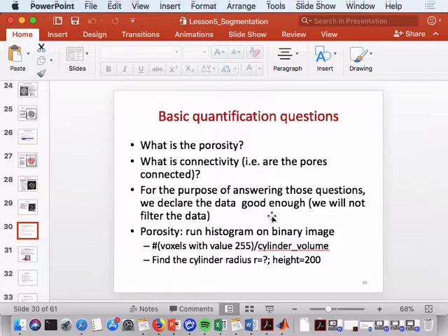The rule of thumb is this: if you have pore sizes on a single length scale, so not a multi-scale situation, then the moment you drop below 5% or so, you're going to disconnect that porosity.